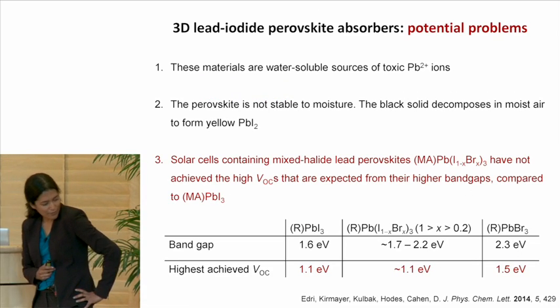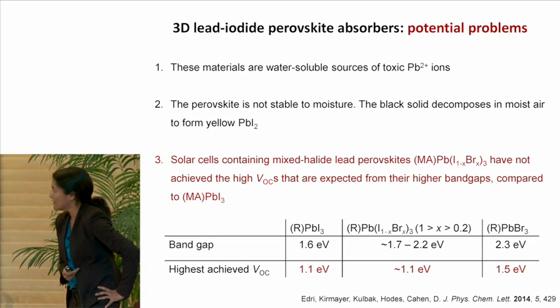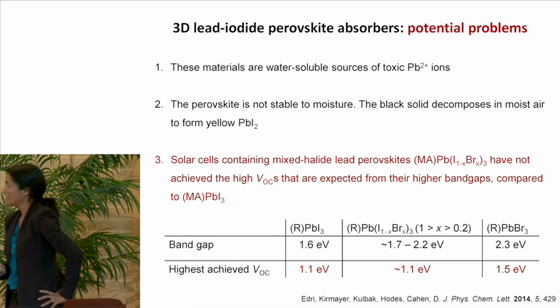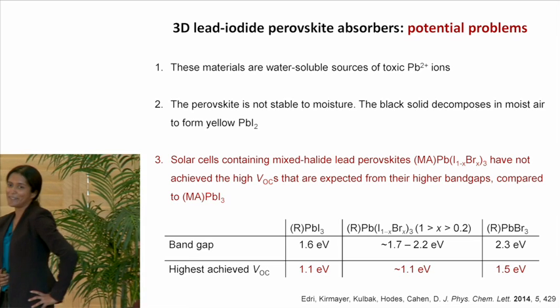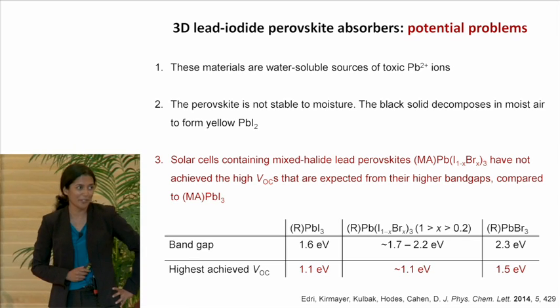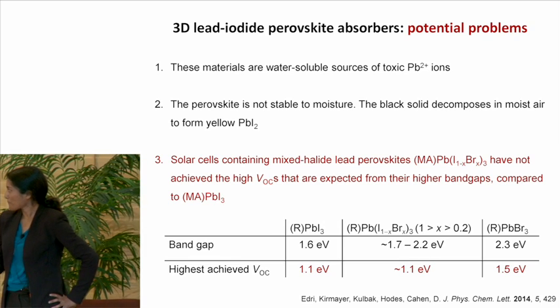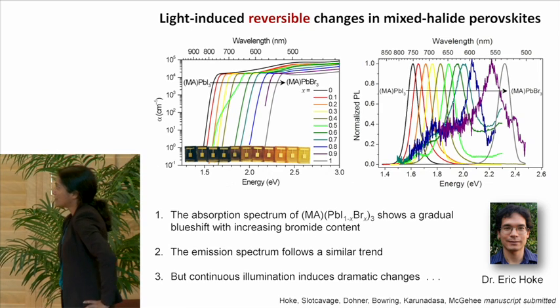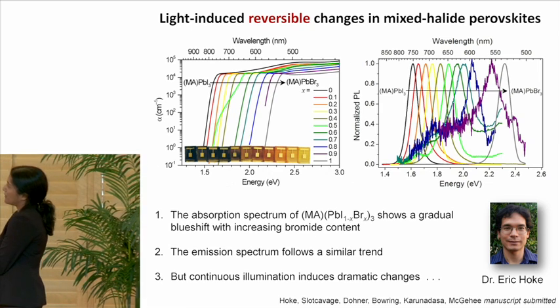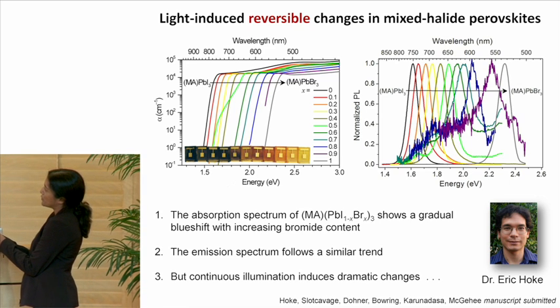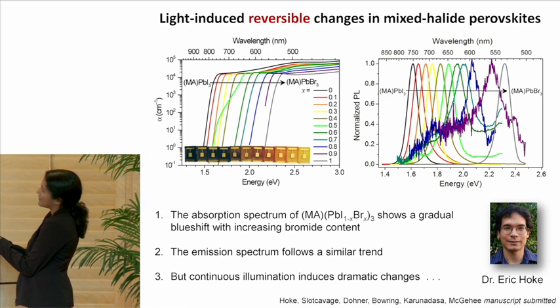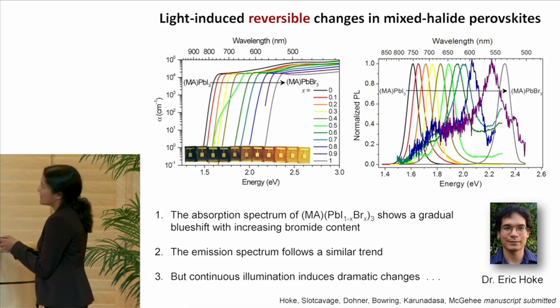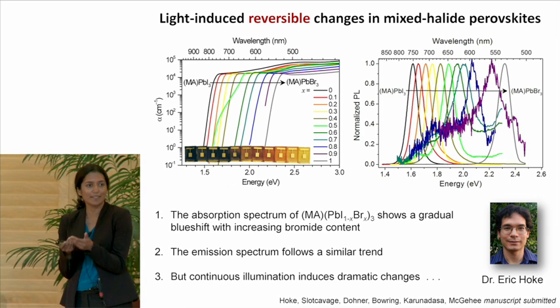So with the rest of my time, I'm going to switch gears and talk to you about some very curious properties we've seen in mixed halide perovskites, in 3D perovskites. So here I show you again the band gap of these materials as you dope in bromide to the lead iodide lattice, and you see this nice increase in band gap energy as a function of bromide content into this